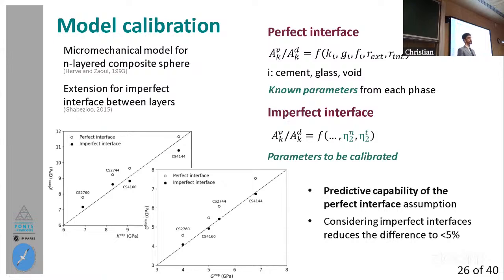Then the model was extended for accounting for imperfect interfaces between different layers, in this case, the spheres and the cement, which was developed already by Ghabezloo in 2015. And in this, we have that the strain localization coefficients now depend on these two compliance parameters, which are normal and tangential compliances, which are parameters to be calibrated and account for allowing a possible displacement in the contact between the sphere and the cement.